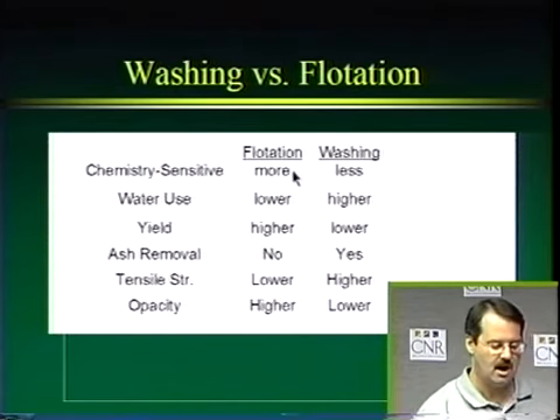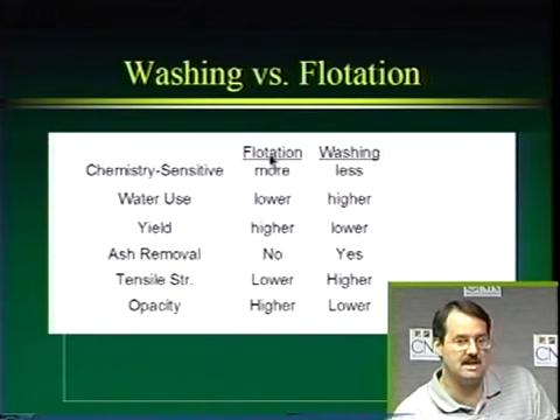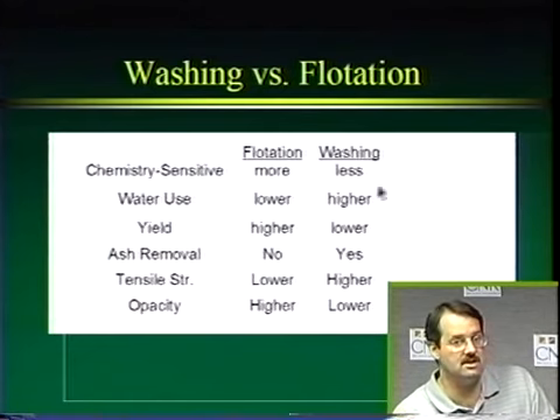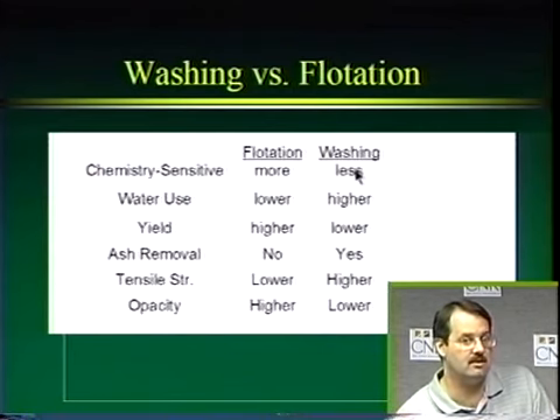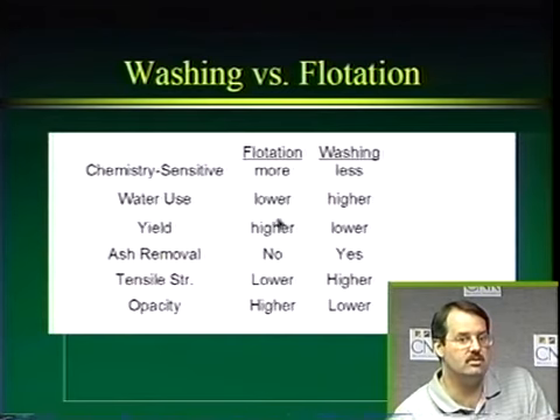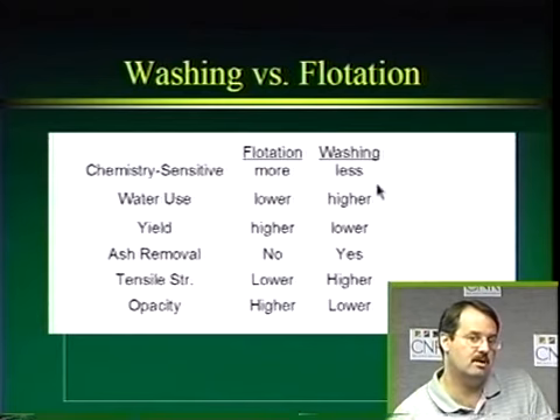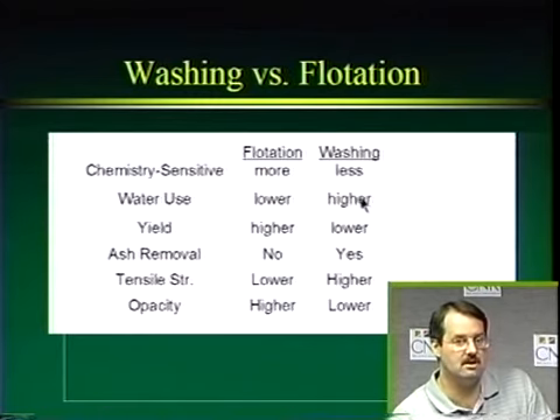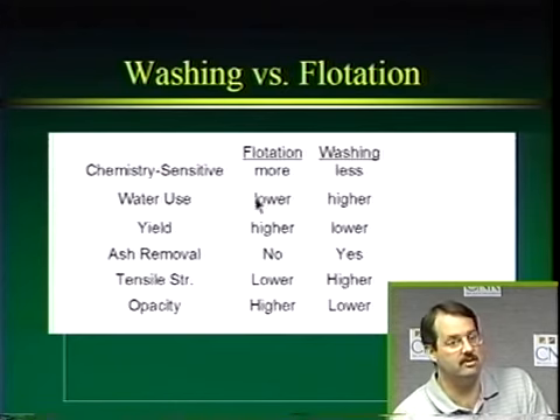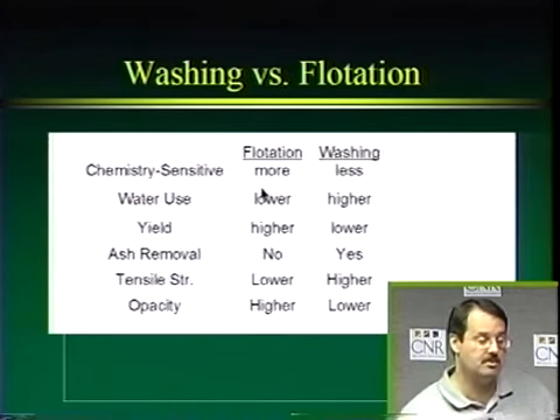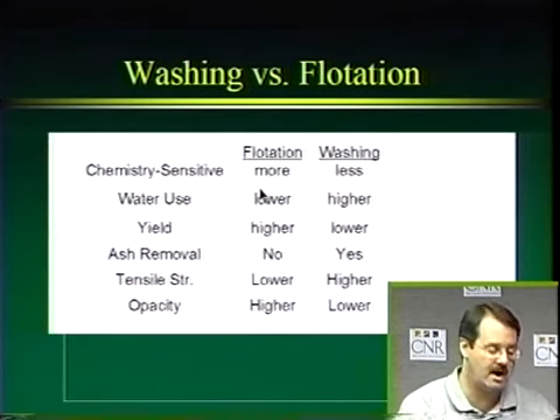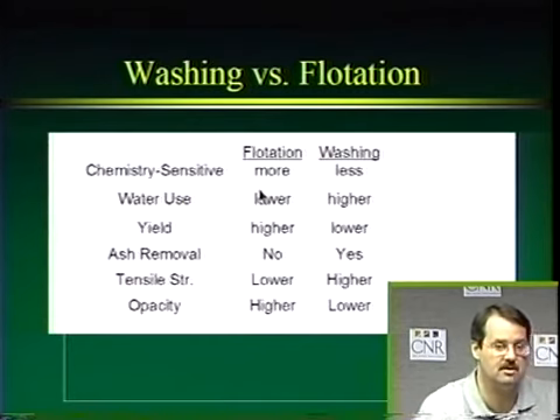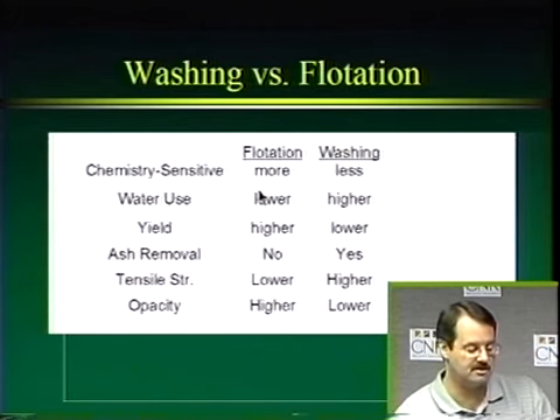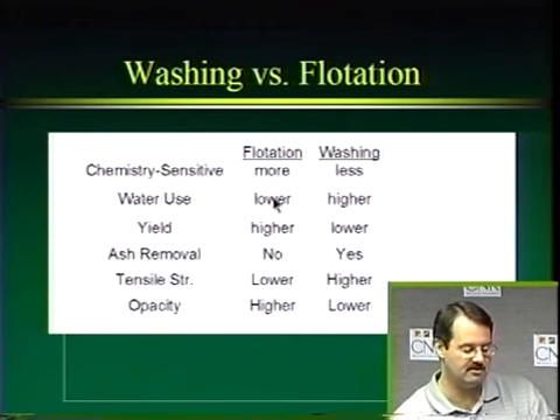Chemistry sensitive. I would have to say that flotation is much more sensitive to chemistry. So washing is a little bit simpler process. All we need to do is add some kind of dispersant and disperse our ink in the water phase. Water use, we use a little bit lower in flotation than washing. But for washing, if we do good clarification and reuse our water, we can be in good shape. In flotation, we also have to get down to low consistency, less than 1%. So if you can combine that with other low consistency operations like cleaning or screening, perhaps the water use might not be as much of an issue.